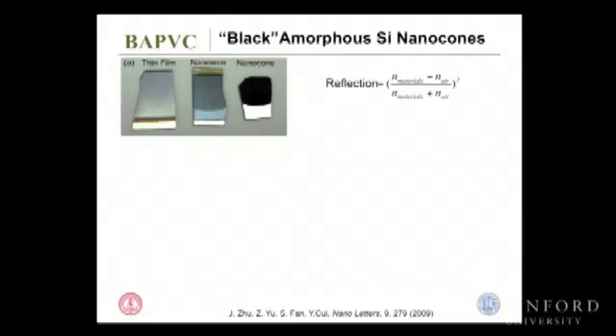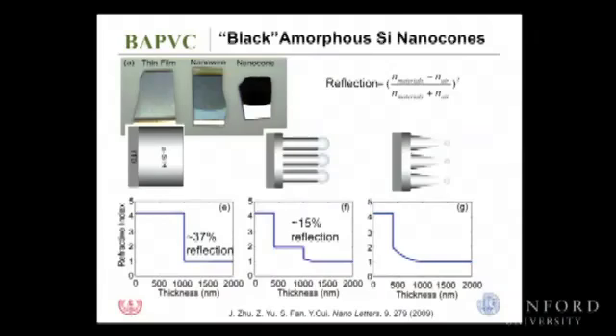We figured out this is actually anti-reflection. Reflection of light is caused by the refractive index difference between the air and your solar cells. Having this nanocone right here, going from air into your nanocone goes through this gradual change in refractive index. Compared to the flat film, there's a lot of reflection. This gradual refractive index really allows all the sunlight to go into your solar cells and get absorbed completely.